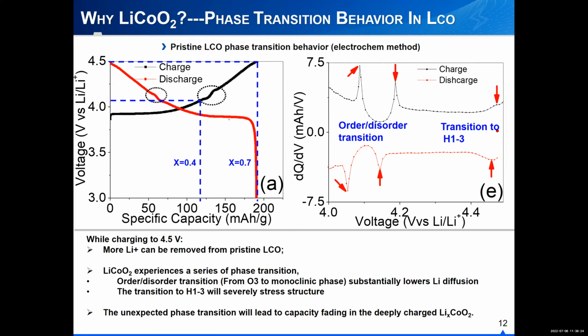So now from this electrochemical data about these materials, we know that when we charge them to high voltage, for example, to 4.5 volt, more lithium ions can be removed from these materials. However, you will find that in the industry, these materials can only extract about 140 or 160 milliampere hour per gram capacity.